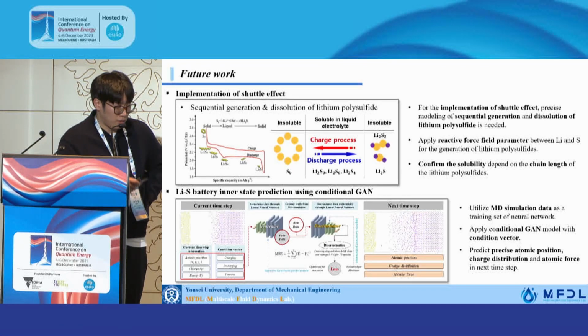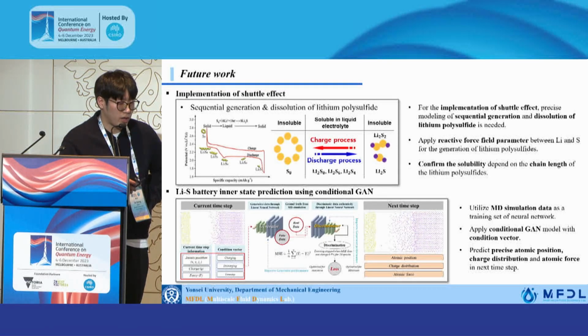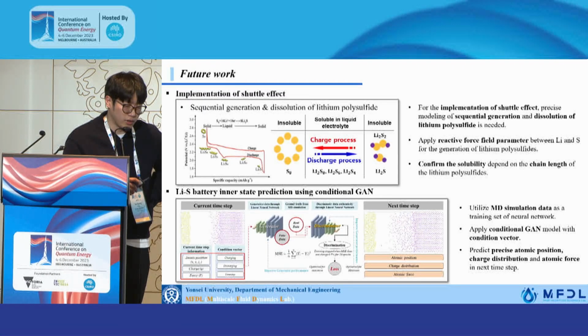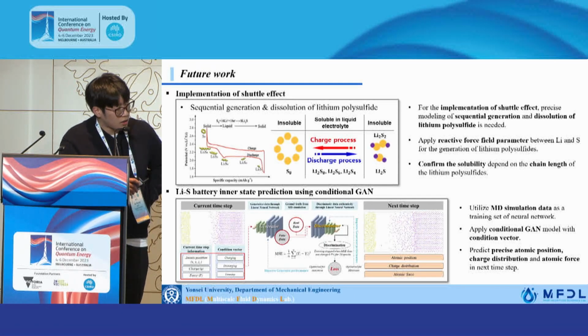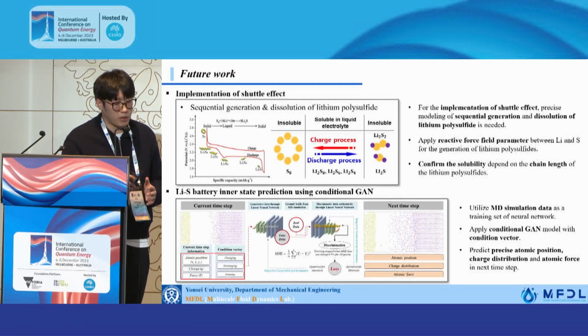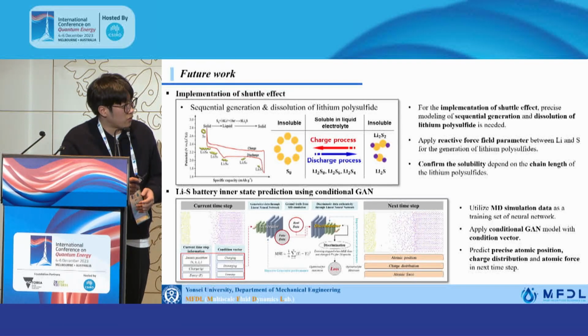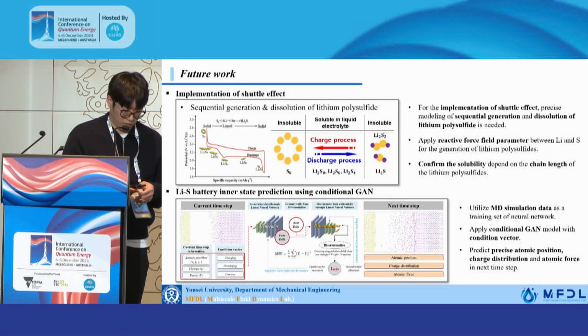I was supposed to model the shuttle effect, but I just confirmed the bond breaking of the molecule. So for the implementation of the shuttle effect, I would apply the reactive force field parameter within the system and confirm the solubility of the lithium polysulfides during the charging and discharging cycle. And the next step is adjusting my domain to the neural network system and predicting the lithium-sulfur battery simulation.